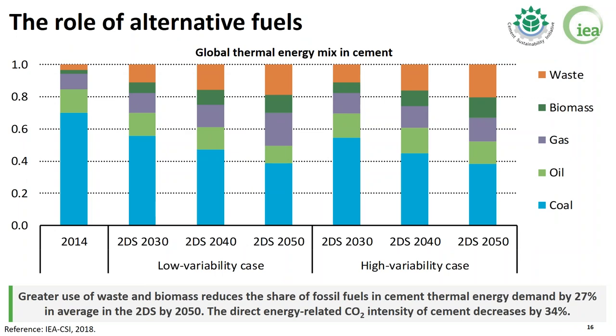In terms of the role of alternative fuels, as we've mentioned in the previous slides, the role of alternative fuels in the global thermal energy mix of cement production is slightly above 5% of the thermal energy consumption. And this is further increased in the 2 degrees context, both in the low variability and high variability cases, so that we are moving from a contribution of fossil fuels around 94% in the base year towards around 70% in 2050 in the 2-degree scenario at the global level.